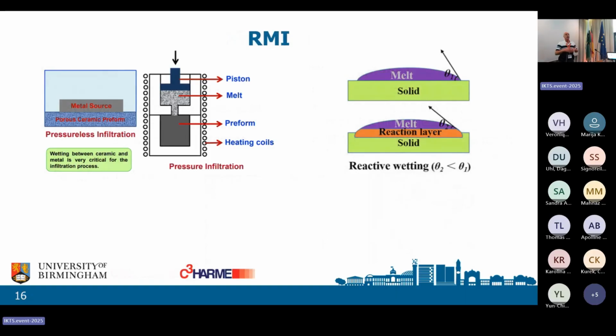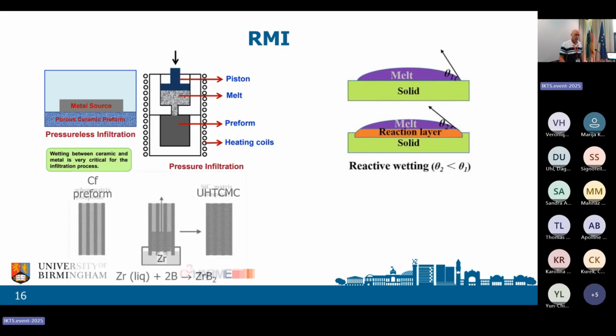Reactive metal infiltration does exactly as the name implies. You take a metal, you melt it, you push it into the fiber preform. And the fiber preforms can again be 2D, 2.5D, 3D. The crucial thing here is the wetting. If it doesn't wet, you've got problems. So you have to have wetting. Not just wetting of the metal on the solid, but when you've developed the reaction layer you want to create, that also has to be wetting. So there's a lot of understanding of wetting and chemistry that is required for doing this work.